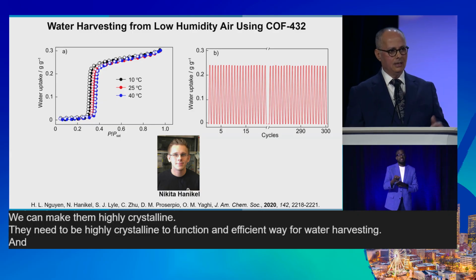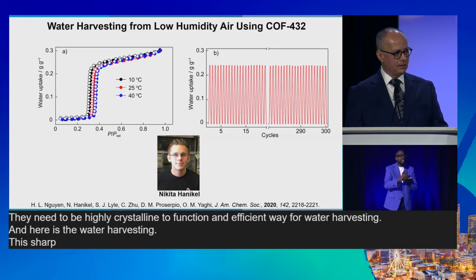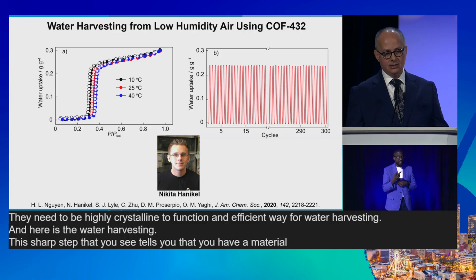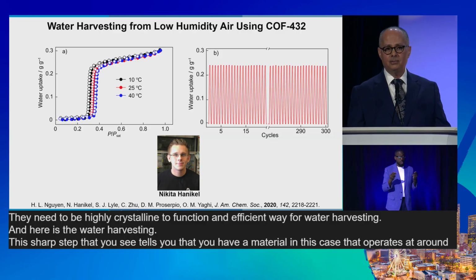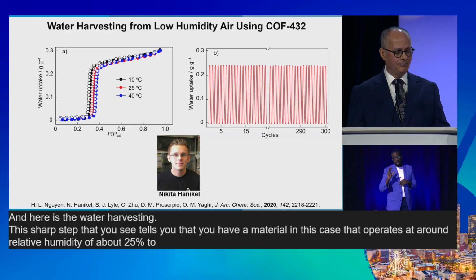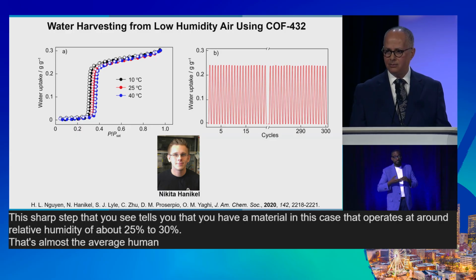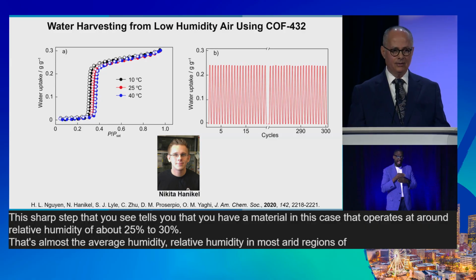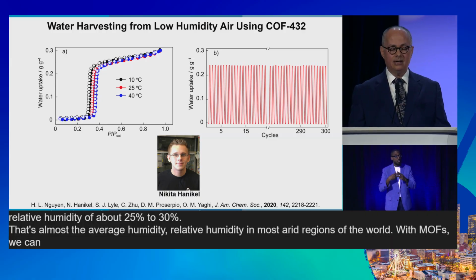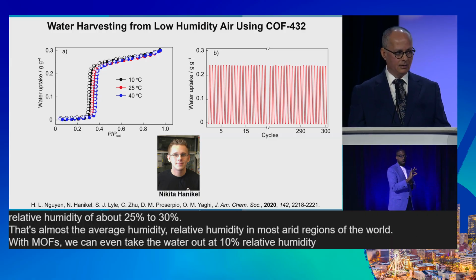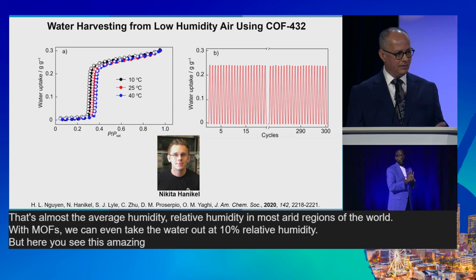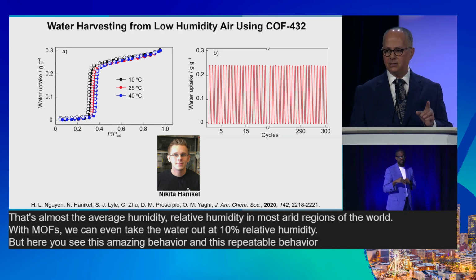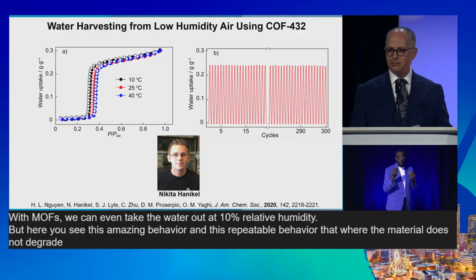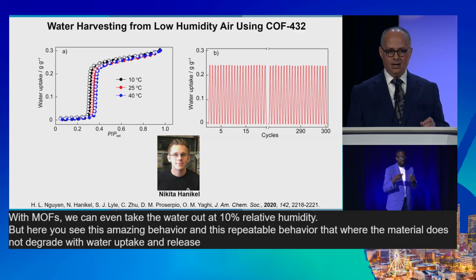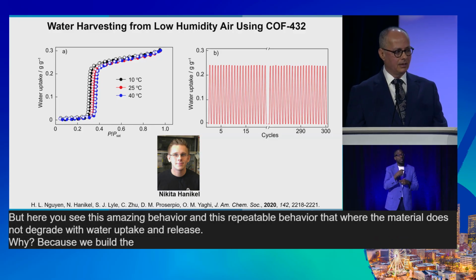This sharp step that you see tells you that you have a material, in this case, that operates at around relative humidity of about 25% to 30%. That's almost the average relative humidity in most arid regions of the world. With MOFs, we can even take the water out at 10% relative humidity. But here you see this amazing behavior and this repeatable behavior where the material does not degrade with water uptake and release. Why? Because we build the material from strong bonds.